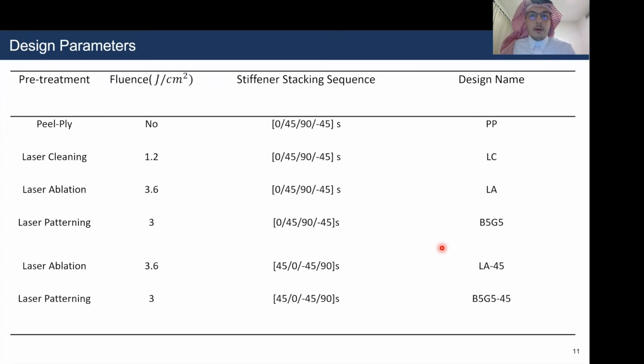So in my study, there are 4 different pretreatment techniques. The first is peel-ply pretreatment, which is a baseline fabric pretreatment. The second pretreatment technique is laser cleaning, which is a low-fluence laser irradiation of carbon dioxide. The third is laser ablation, a uniform laser ablation, which is a high-fluence laser pretreatment, and the fourth is laser patterning, which is an alternation between laser cleaning and laser ablation.